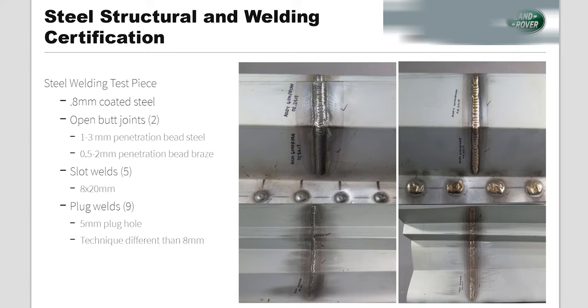So what you're seeing on the right side, once again, is the silicon bronze. On the left side, you're seeing a very similar type of weld. That is done with steel electrode wire, same process, hit it, let it cool, hit it, let it cool. But the part that really throws people when they come to weld this program, they go like, hey, I've been welding steel for a long time, this shouldn't be too bad. However, to my knowledge, and if you look on the bottom left, I don't know of any OEM that requires a minimum, I'm saying minimum, of 1 millimeter height bead on the inside. And it can't have any flaws when you're all done.